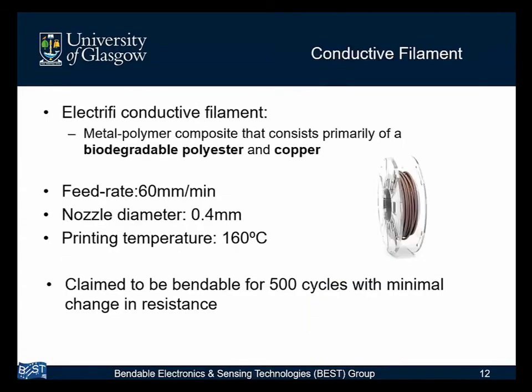Now, to look at the conductive interconnects for our 3D circuits, or particularly our bendable 3D circuits, we're looking at inks, as well as conductive filaments. One conductive filament which we went for is commercially known as Electrifi conductive filament, which is based on copper fillers and a biodegradable polyester. This was reported to have quite low resistivity, and even one study showed its bendability for around 500 cycles. So we thought it would be a good place to start in terms of this type of material study.